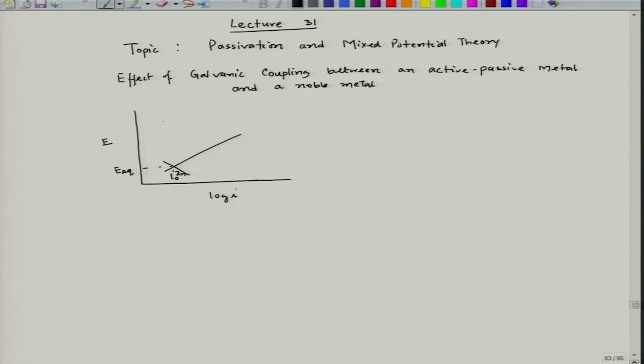So, when it is exposed to a hydrogen ion containing electrolyte like acid, it will have hydrogen evolution reaction on its surface. So, let us say this is the hydrogen evolution reaction on its surface. So, this point becomes E equilibrium and this is I naught hydrogen on zinc surface, and this becomes my I corrosion of zinc.